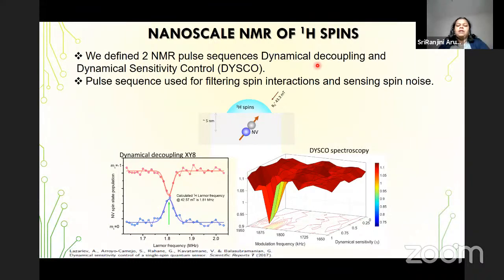Here we have an NV center buried about 5 nanometer from the surface, and we have a proton bath, basically ultra pure water, and apply an external magnetic field. And when we have this going on, we can actually sense the Larmor frequency of the proton at 1.81 megahertz.